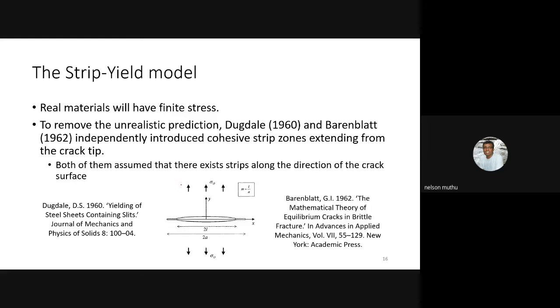Then he had to extend the physical crack tip by a fictitious amount, that is lambda, in such a way that the equilibrium condition is still satisfied. The equivalence is established on both fronts. We can still apply LEFM principles, therefore we can find the SIF for the extended crack, and also we can equilibrate. There is an equilibrium between the extended crack and the elastic singular crack tip stress field. There is an equivalence. So in that sense, it is not violating the equilibrium. At the same time, it is able to extend the crack by lambda and accommodate the LEFM principles in that framework.